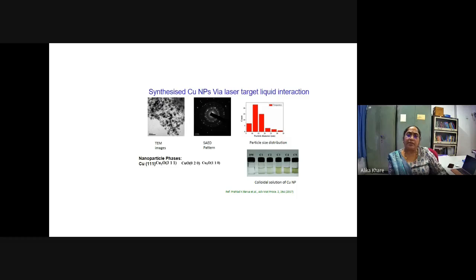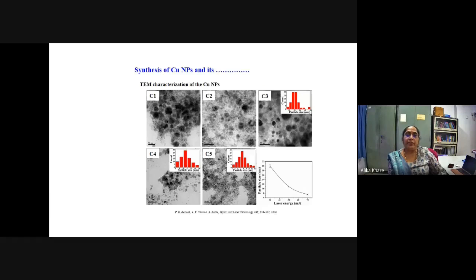Here the liquid after laser exposure is shown. First is the pure distilled water, then the target exposed for 5 or 10 minutes, then 20 minutes, then 30 minutes, and then from here we change the power. One can see that with changing conditions, the color of the liquid changes because the particle size is changing and their surface plasmon resonance is changing, which is why we see different colors in the liquid.